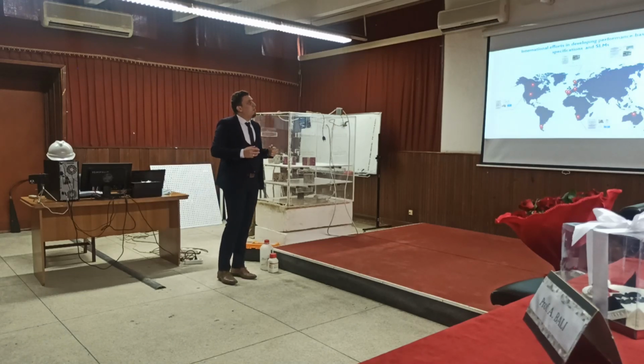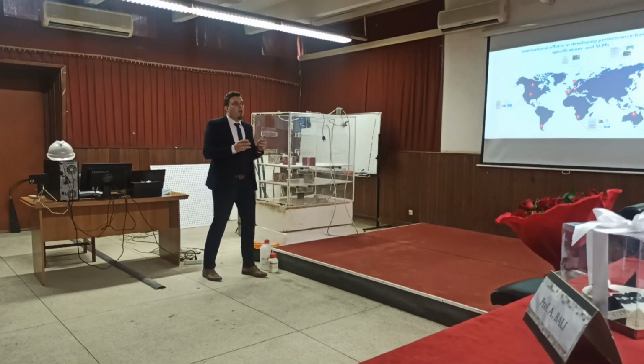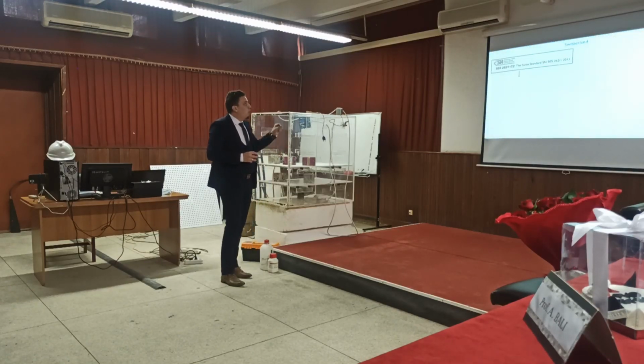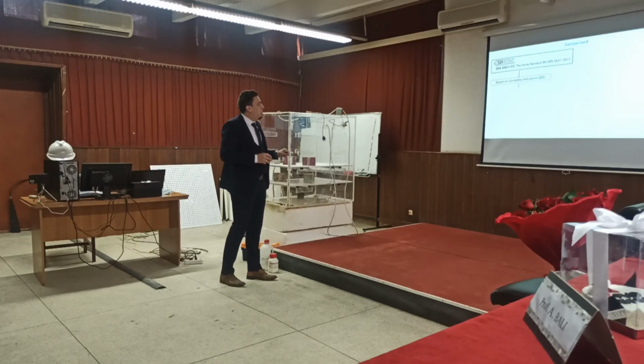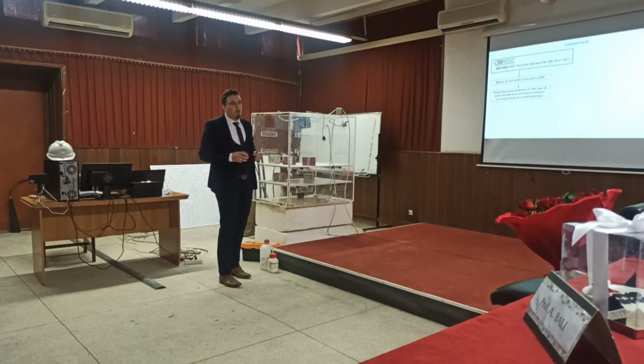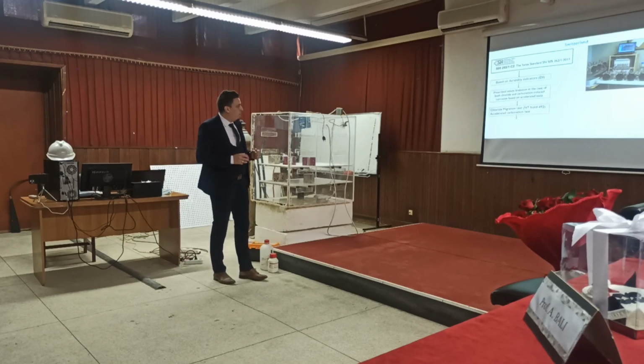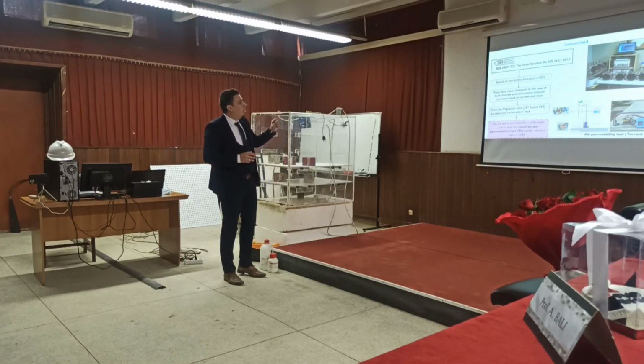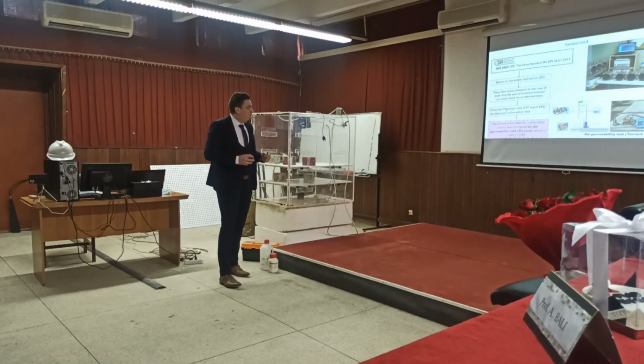In this slide, I will give you the international effort in developing performance-based specifications in service life models. The country that is very advanced in developing this specification is Switzerland. In Switzerland, they work with a durability indicator, and they prescribe value limitations in both cases, chloride and carbonation-induced corrosion. We have the chloride, and we have the accelerated carbonation depth. And they link the DI, prescribed for conformity control, to the air permeability, which is called the Torrent test method.